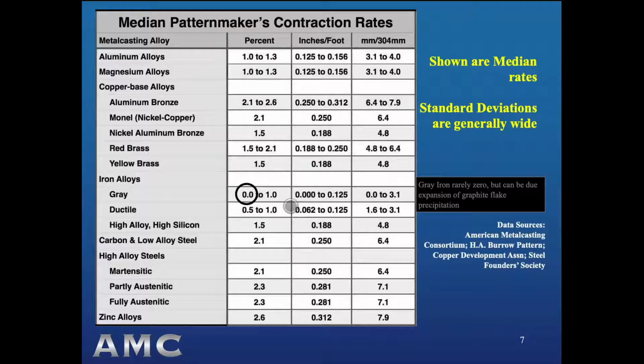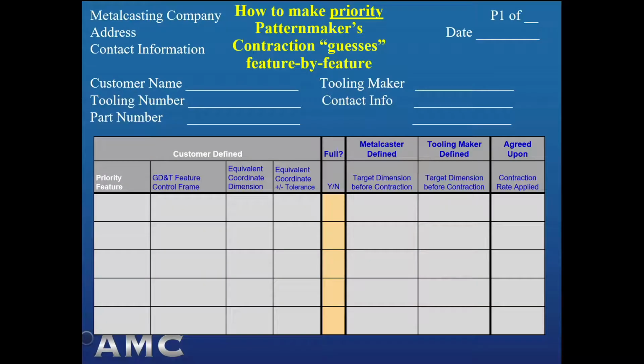Look here at all of the many metal casting alloys, and look at the difference in the center column, which is the standard parameter, inches per foot of contraction, and just look how much the median rate for each of these alloys differs. When I was making casting, here's a chart that I used to help me and my mold cavity tooling builder collaboratively make better pattern maker's contraction rate guesses.